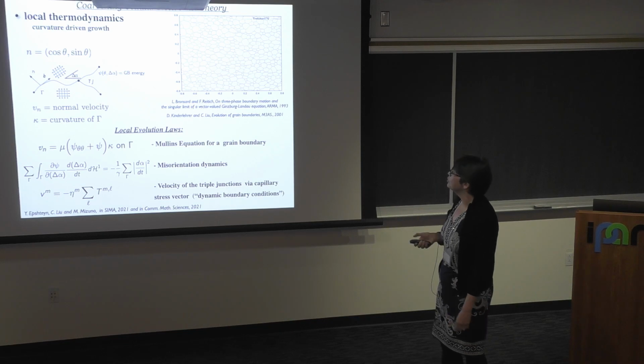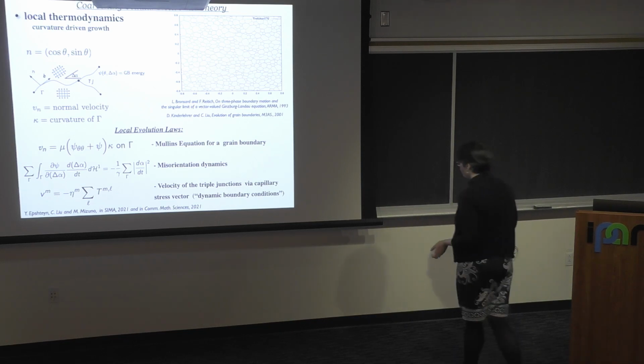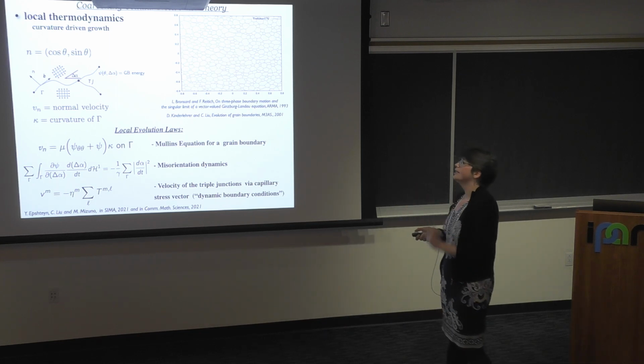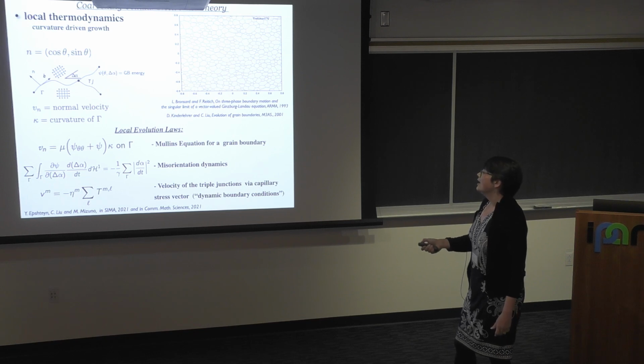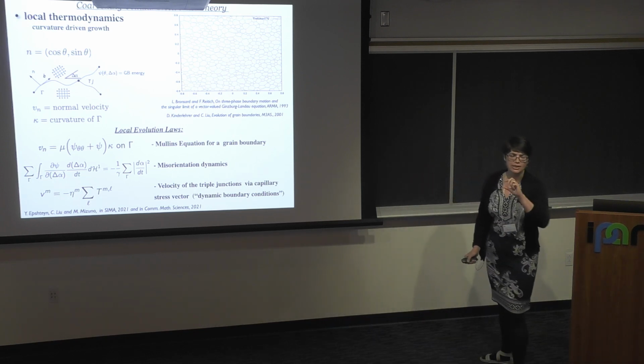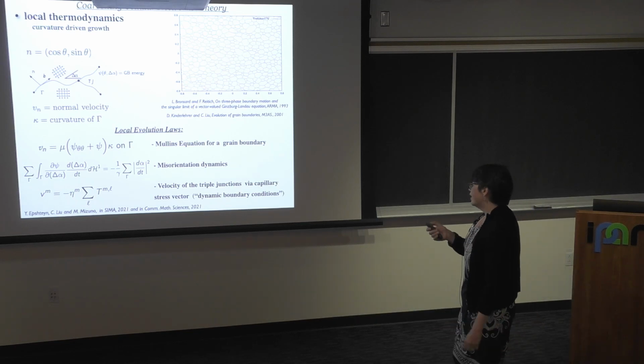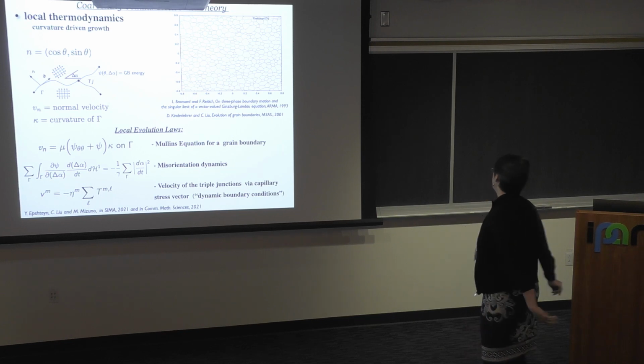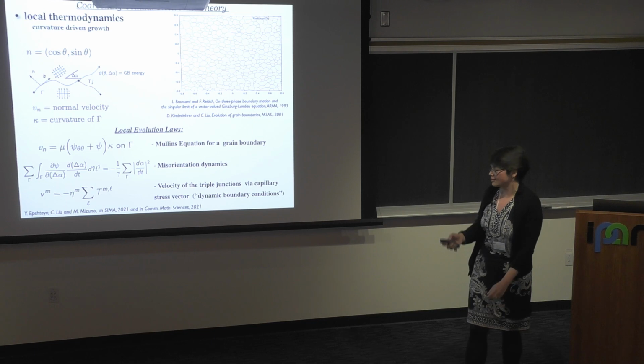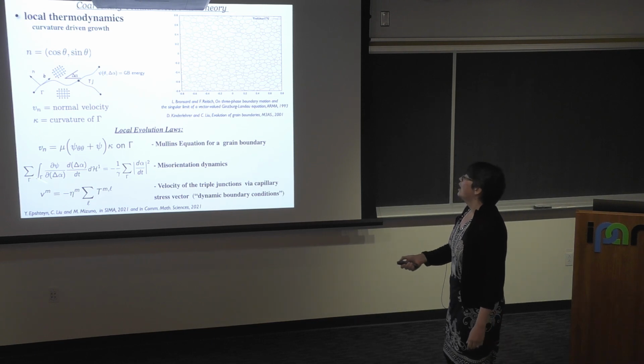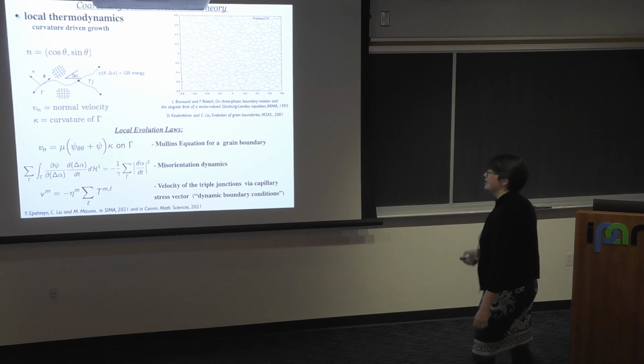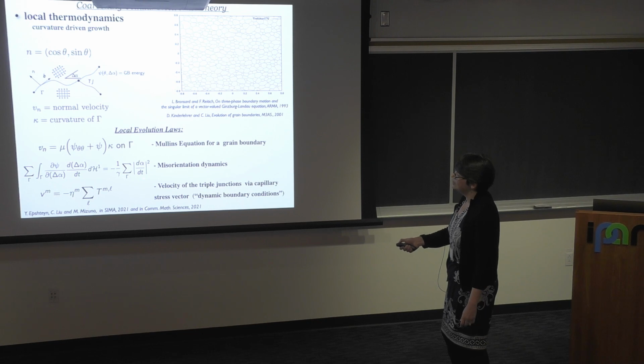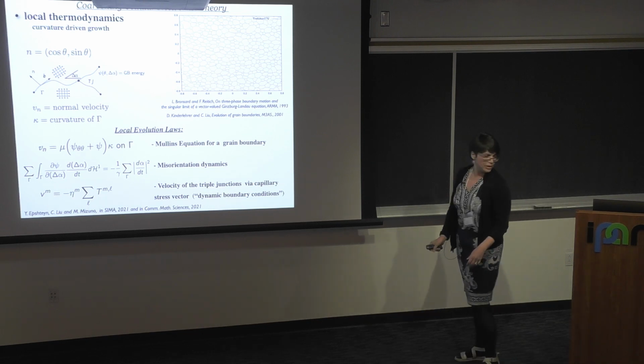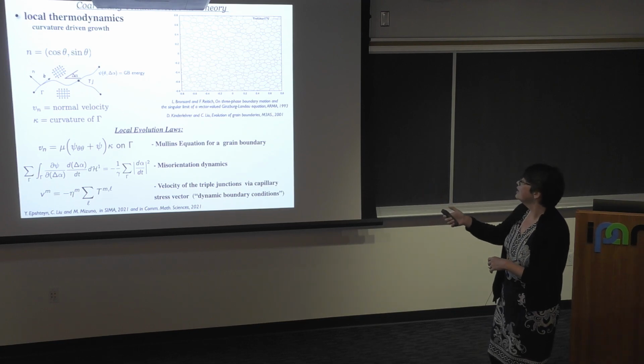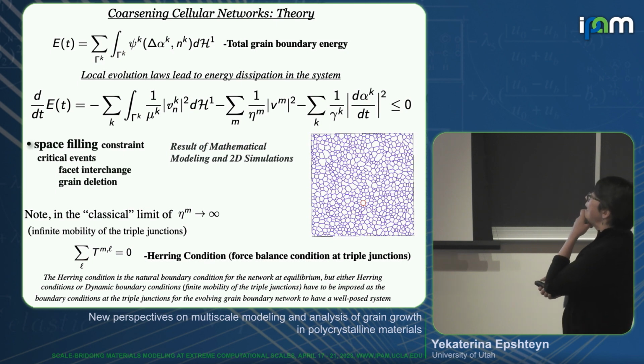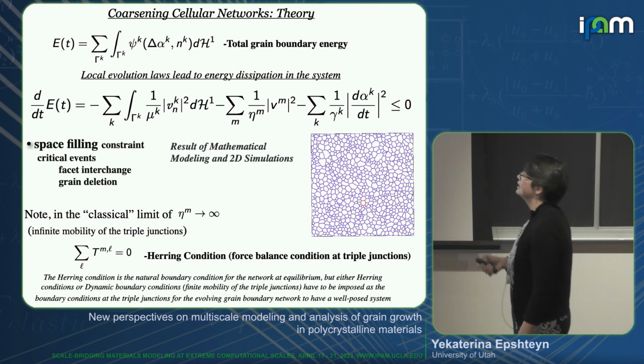So in addition, in our model, we also wanted to introduce effect of dynamics of misorientations or dynamics of reorientation, and in some way, it can be viewed as incorporating possibility of grain rotation, or could be also introduced to model actually disappearance events through introducing additional dynamics of orientations or dynamics of misorientations, and we have associated time scale to that, gamma, which is related to dynamics of orientation, so dynamics of misorientation. So these are our local evolution laws, and we can define the total grain boundary energy.